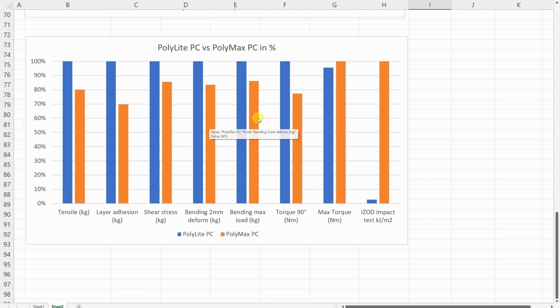Now the polycarbonate, here we have a little bit of a different story. Again, yes, the PolyLite was better compared to the PolyMax on all mechanical tests, except here on maximal torque, but the difference is not so big. But look at this impact test. Here we have huge differences. The PolyLite PC is extremely brittle, but the PolyMax PC is a very tough material. So in this case I would definitely always choose the PolyMax PC because of these specifications.